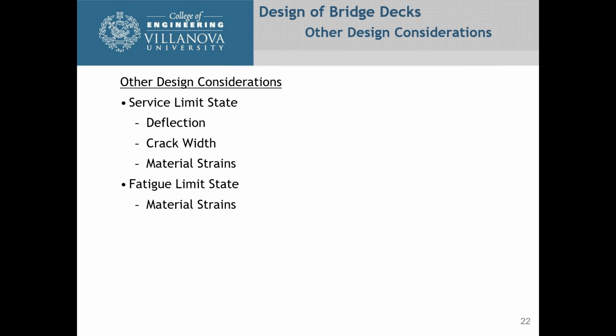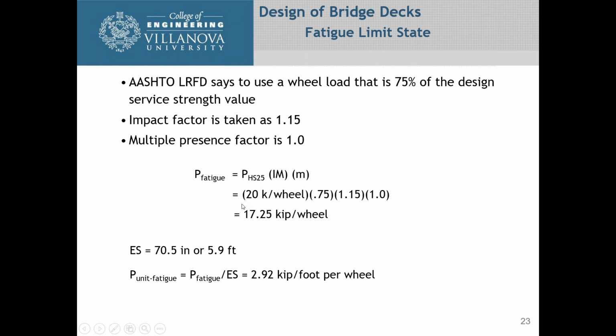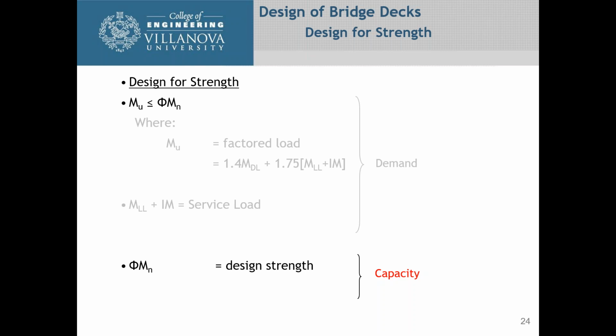The other things we're looking at are service limit states and fatigue limit states. For the fatigue limit state, AASHTO says that you use 75% of the design service value, the impact factor is 1.15, and your multiple presence factor is 1. So your loading for fatigue ends up being 17.25 kips per wheel, and you divide that again by the 5.9, and you get 2.92 kips per foot along the beam. Those give you the two loading combinations we're looking at, service and fatigue. And now let's look at the capacity of the beam.